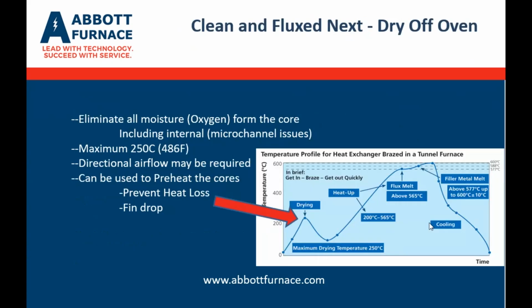So now you have a clean part and it's fluxed. We're looking at the dry off oven at this point. So the dry off oven is going to eliminate all of the moisture, or specifically the oxygen from the core, including the internal parts of the tubes.